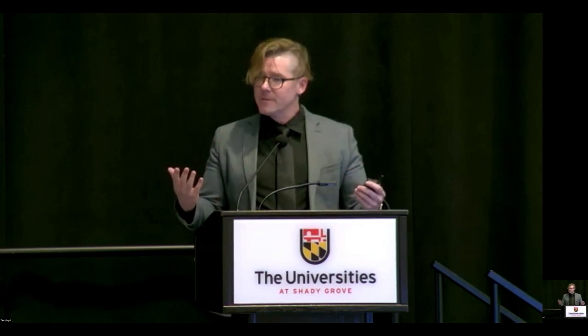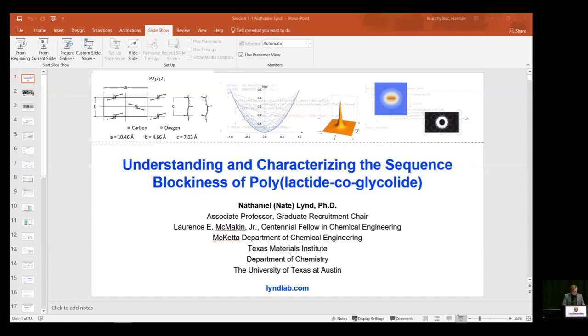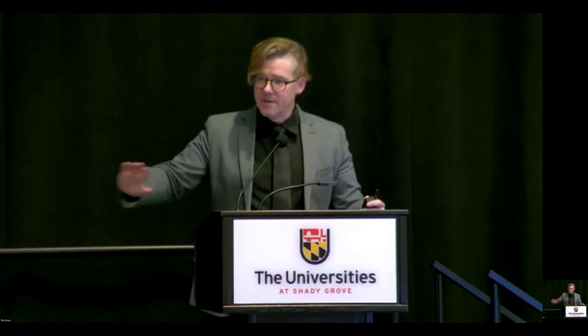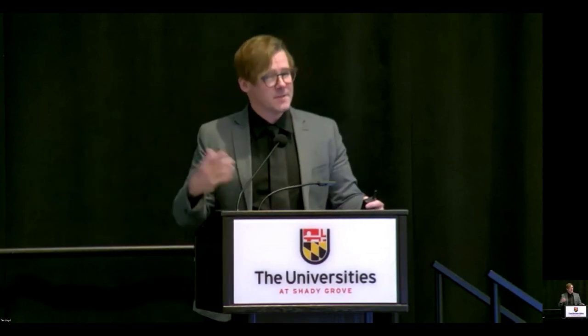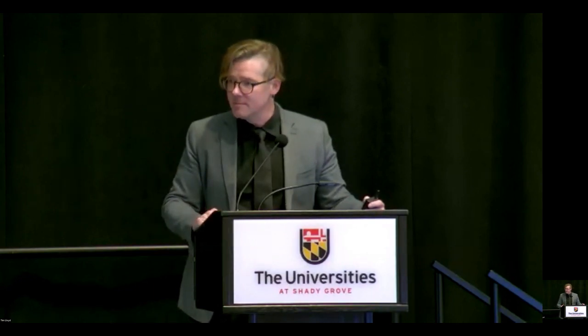There are a number of macromolecular characteristics of PLGA, and I'm not going to be able to address all of them, but in particular, we're going to look at how one might establish sameness in terms of the lactide and glycolide sequencing along the polymer backbone, which does impact polymer properties. So here's a pretty complicated chemical scheme that underlies the chemistry that results in the formation of polylactide co-glycolide. In the upper left-hand corner, we have forward propagation, where the different reactivities of lactide and glycolide dictate incorporation statistics. But this is an equilibrium polymerization. So monomers add to the polymer chain, but they can also essentially fall off and go back into the mix. We also have 2 types of transesterification, both interchain and intrachain, where neighboring chains or a single chain can exchange segments with its nearest neighbor or itself.